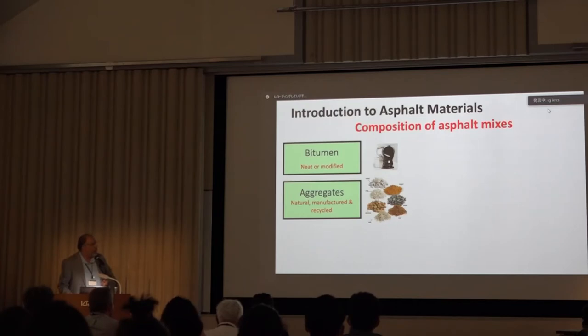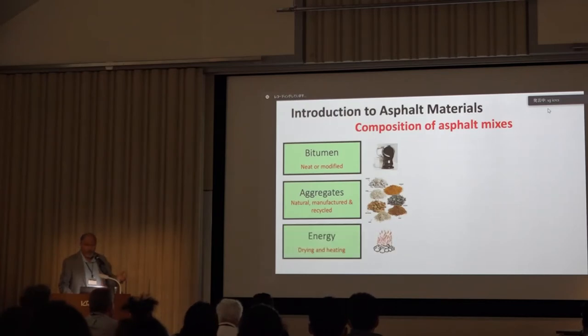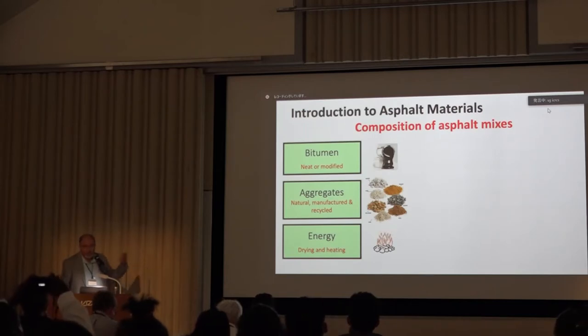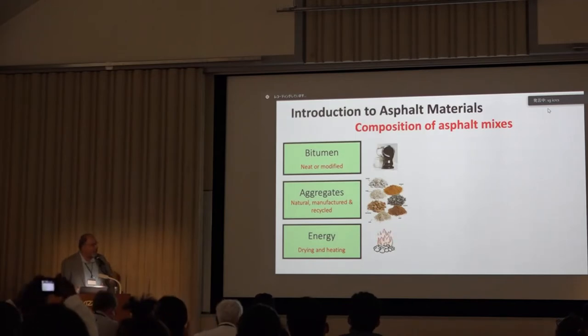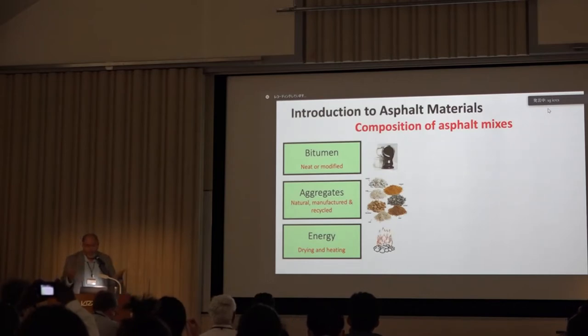So asphalt is a composition, like a concrete actually, composed of aggregates and a binder, which is the bitumen, or the asphalt cement, or asphalt binder, depending on where you are, mixed together with some energy. Energy to heat the aggregates to dry the moisture, because we don't want water in the mix, but also energy to mix them all together.